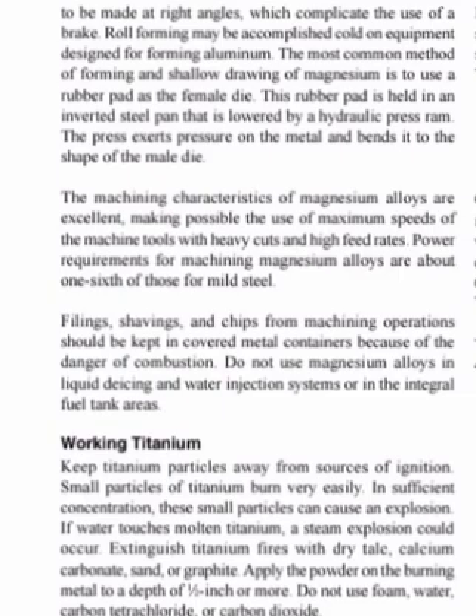The press exerts pressure on the metal and bends it to the shape of the male die. The machining characteristics of magnesium alloys are excellent, making possible the use of maximum speeds of the machine tools with heavy cuts and high feed rates. Power requirements for machining magnesium alloys are about 1/6 of those for mild steel.